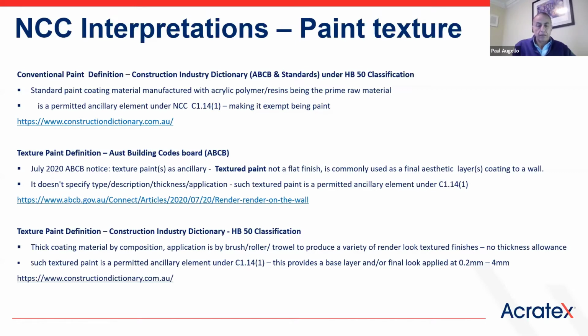So under that ruling, it sits into your C1.14. And this particular layer, if we call it a layer, is generally applied between 0.2 of a millimetre and can almost go up to 3-4 millimetres, depending on the composition of the product and what its fit for purpose is. But the core part of it is that they are all the same when you look at a textured paint versus a normal conventional paint. They all have the same type of polymer compositions within them.